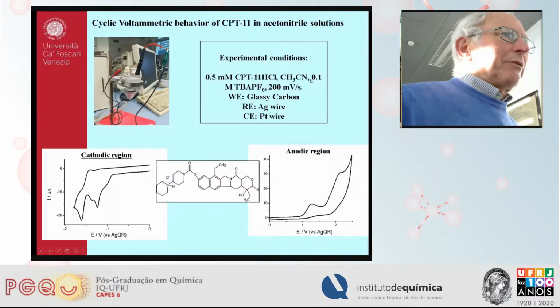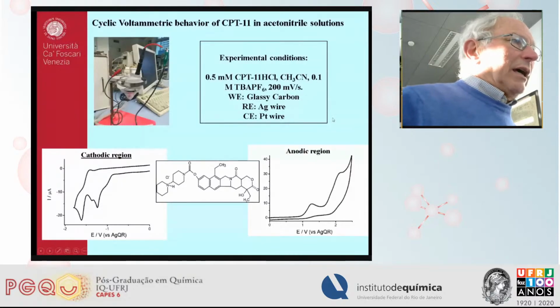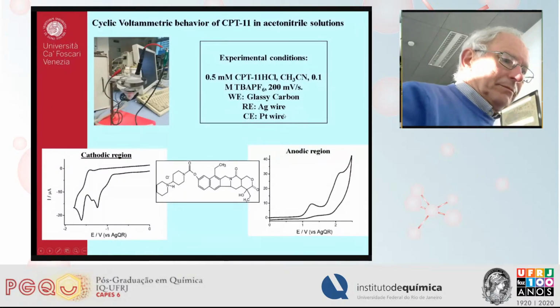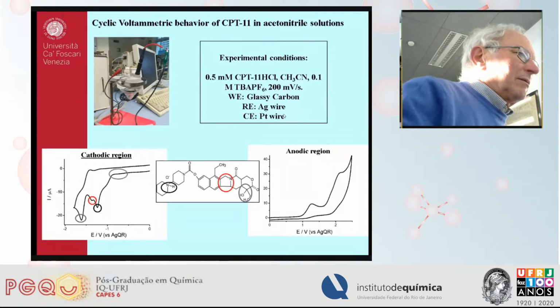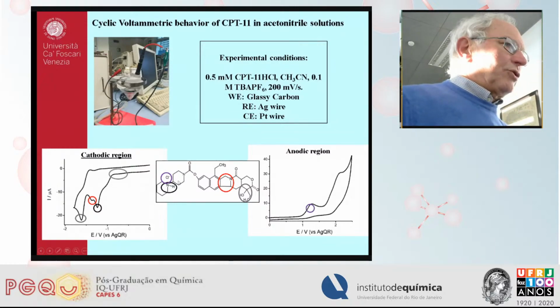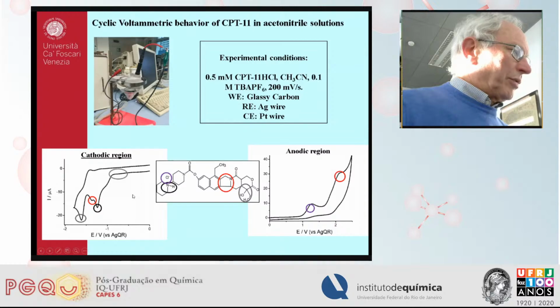After a screening of various solvents which could be useful for the detection of this compound, we ended with acetonitrile as the most useful solvent. For electrochemical measurement, we have to add a supporting electrolyte, and we realized that TBA-PF6, tetrabutylammonium hexafluorophosphate, is a good one. The working electrode is simple: a glassy carbon, which is commercially available. We used a reference electrode which was a silver wire, in order to avoid any contamination from a classical reference electrode, and the counter electrode was a platinum wire.